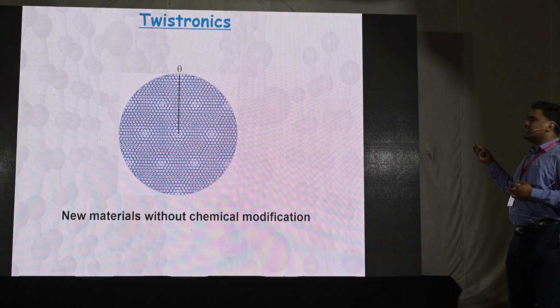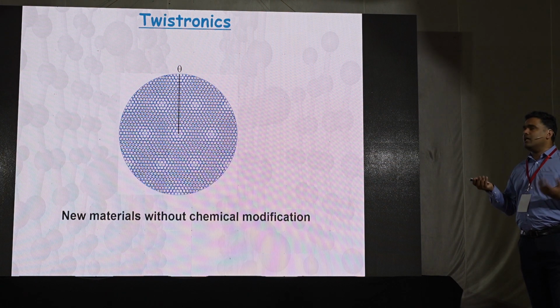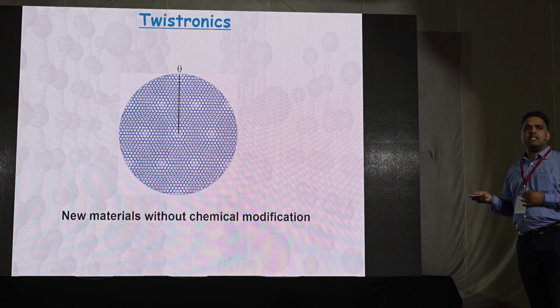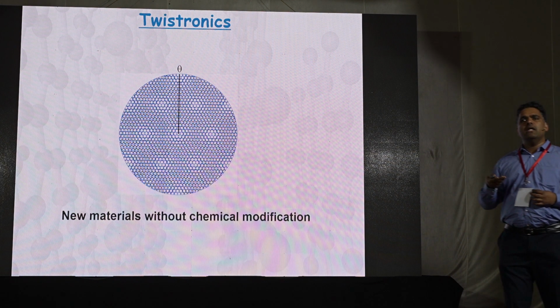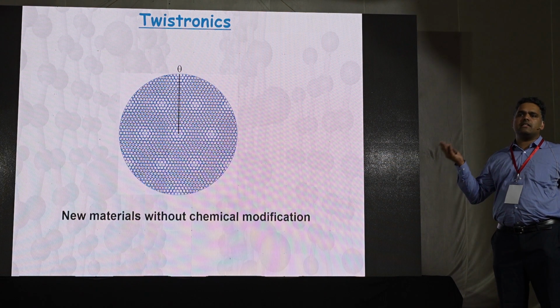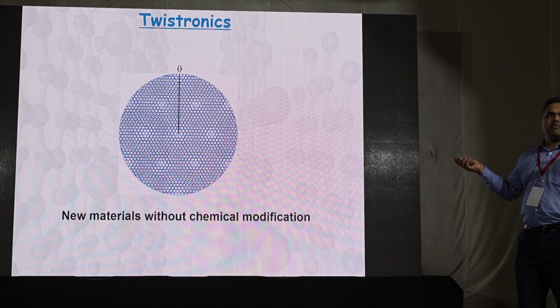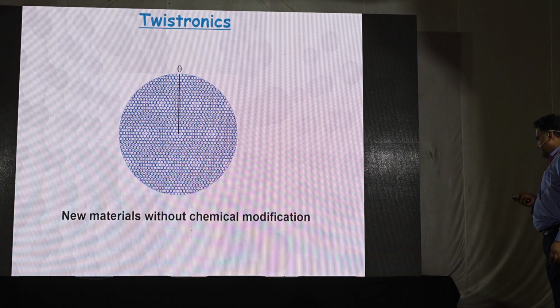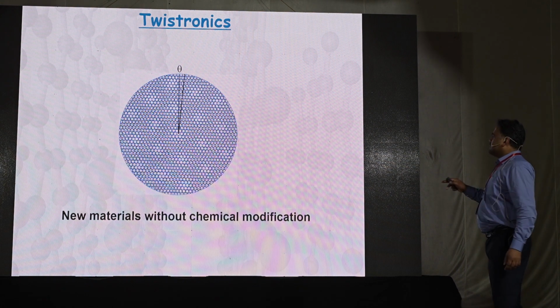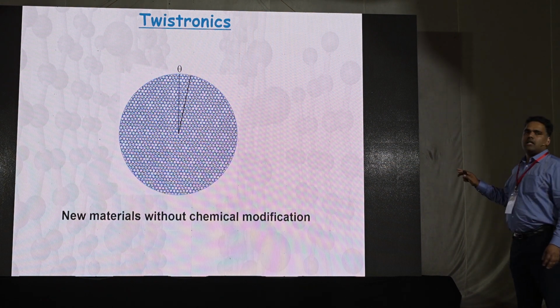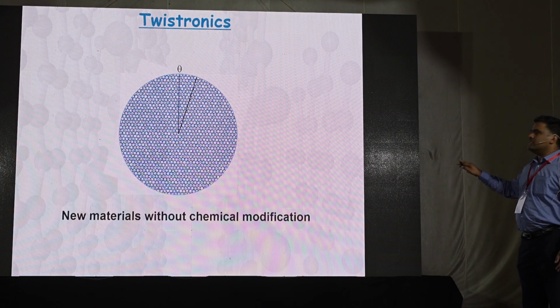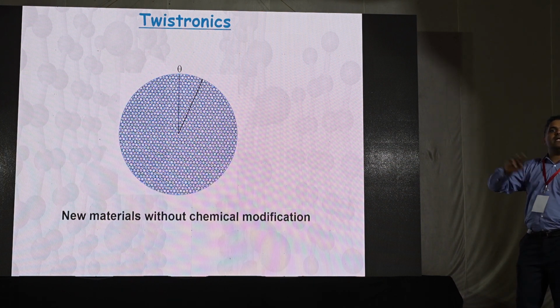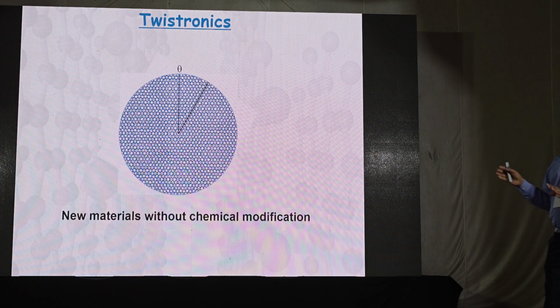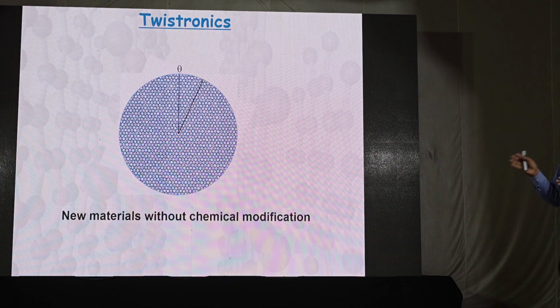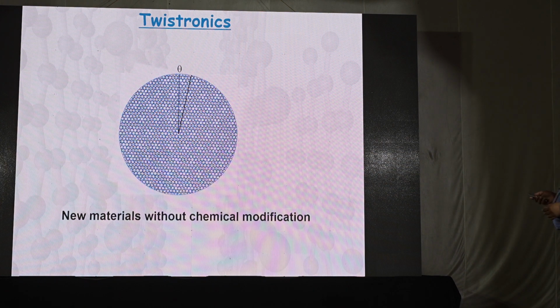So this field is really booming, and it's called twistronics. You can create materials with exceptional properties. Even people made superconductors, insulating states, everything is there within these 2 layers. As I said, depending on the twist angle, you get different types of lattice, and depending on the lattice constant, you create different properties. So this is a physicist's method of making new material without any chemistry, by just rotating 2 layers of atoms. Now,